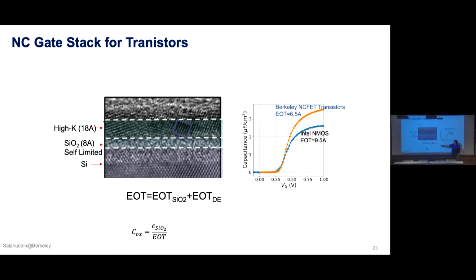So what happens is we have to add the thickness of silicon dioxide and then add the thickness of this dielectric layer normalized by the permittivity ratio. So that's why it is often called the EOT. If you look at it, what we expect to get is 8 angstrom from silicon dioxide plus something.